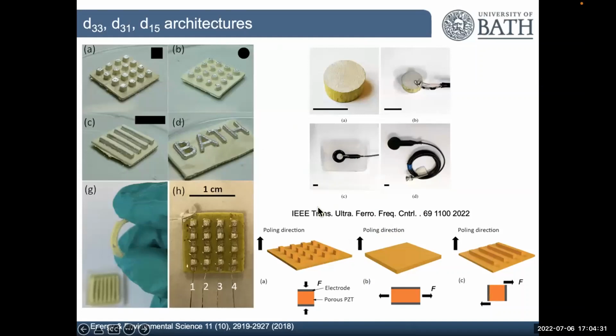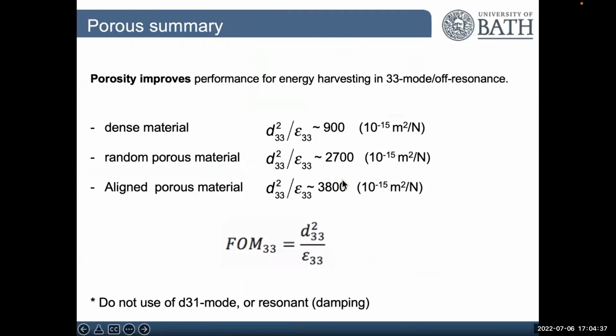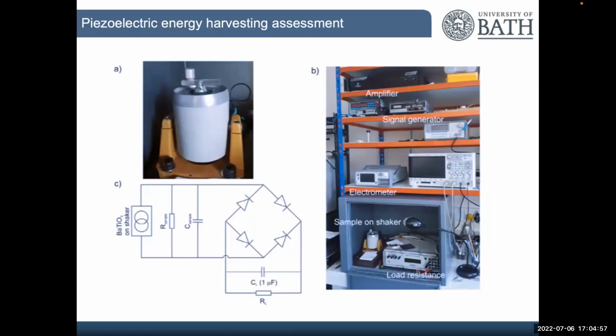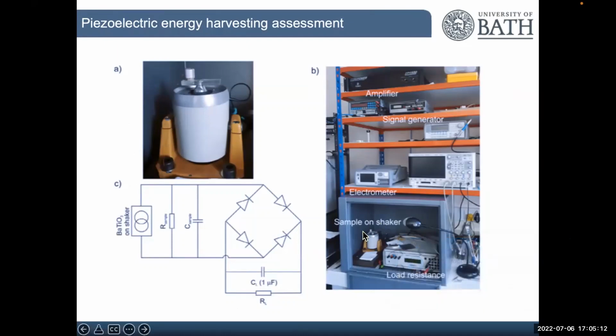And create a wide variety of sensors and energy harvesting structures. And by doing that, we can get the figure of merit even higher. So remember, the dense material was around 900, and the aligned porous materials are a factor of 4 higher. So better in terms of energy harvesting performance, but also improved in terms of voltage. Lots of people said, oh, figures of merit are fine, Chris. Does this actually work? Because you're removing material, you're removing the active material, but you're generating more energy, or you're generating a higher voltage. And so I had to prove that.